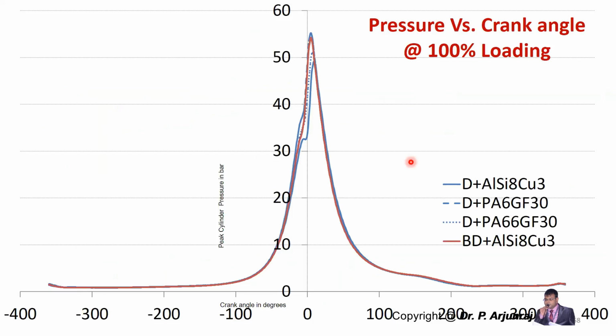And this is the pressure versus crank angle. You can find that diesel with PA6 glass fiber 30 air intake manifold results in a high peak pressure during combustion, and this is because of the improvement in air density with respect to the air intake manifold. In the case of biodiesel with aluminum and also with PA6 glass fiber, the peak pressure is slightly higher, and this is because of the reduced ignition delay period and the use of the PA6 air intake manifold contributing to improved mixing of the fuel air ratio and enhanced combustion performance.